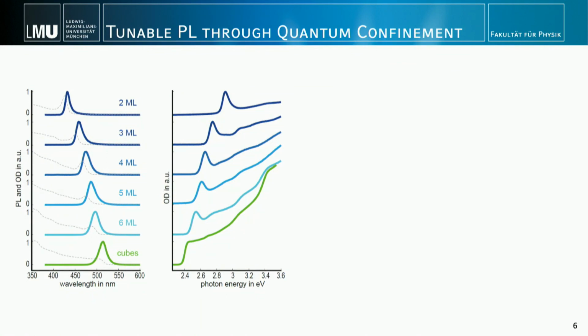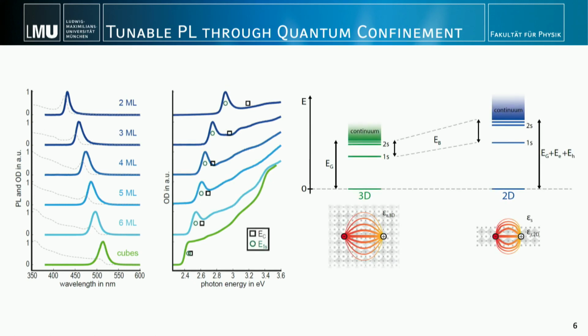Now when we look at the absorption spectra, this was very interesting to see the first time. What you see when you look from the bottom to the top, so from cubes towards thinner platelets, is a peak rising up at the absorption onset. This is a so-called excitonic peak. And what we observe is basically a transition from a 3D to a 2D material. As we decrease the thickness, the role of excitons becomes more dominant. This was a word I also mentioned in my title. Excitons are bound electron-hole pairs. So in these nanoplatelets, electrons and holes are not free, but rather bound and stay together, which is also beneficial for emission. So this is the tunability which could be achieved.